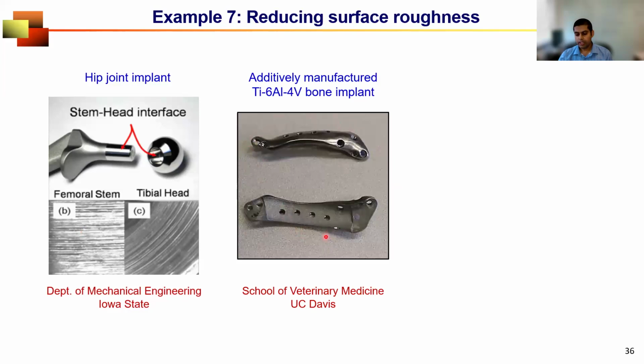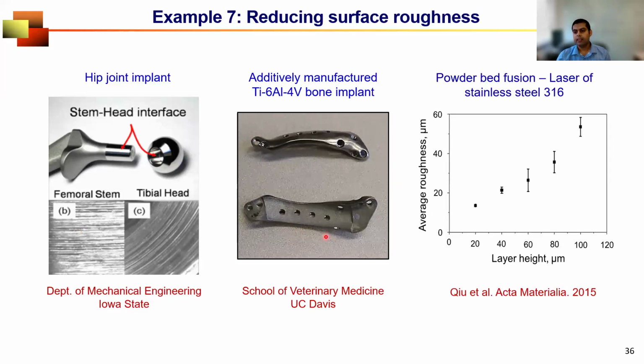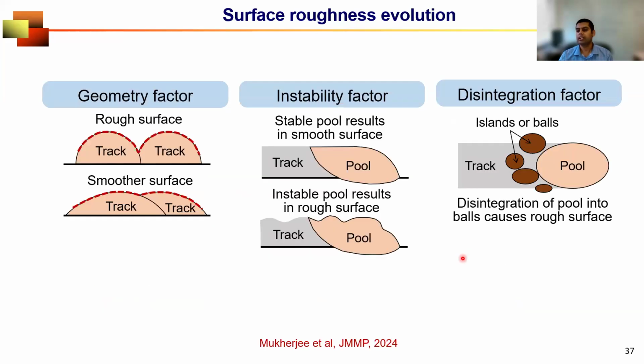One way to achieve good surface roughness is to use very thin layers. In additive manufacturing, we use layers that are thinner than a human hair. If you can reduce the layer thickness, even slightly, then you should be able to reduce the roughness. But at the same time, if you print your part with a very thin layer, you will slow down the productivity. It will take more time. So there has to be a trade-off, and to achieve that trade-off, we need modeling and machine learning.